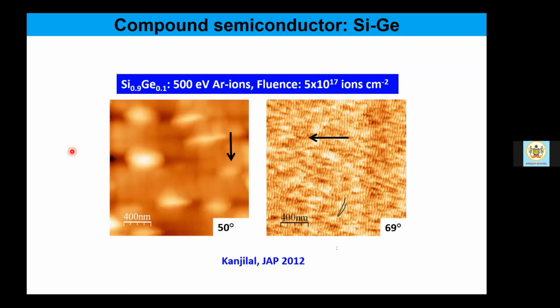We get to see, as we vary the incident angle from 50 degree to nearly 70 degree or so, some isolated island structure formations got initiated at 50 degree, but then at an incidence angle of 70 degree or so, close to that, we get to see beautiful ripple pattern formation.